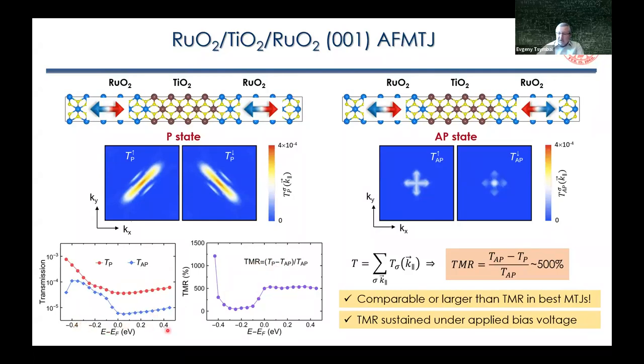So over the whole range of energies, we see quite substantial difference between transmission for parallel and anti-parallel states and quite sizable TMR. So it's somewhat reduced in this region, but even here you have a sizable 50% or larger tunneling magnetoresistance effect. So we can argue that even in the presence of applied bias voltage, we should have a sizable effect. Now I would like to discuss the effect of interfaces. I've mentioned already that interfaces are quite important.